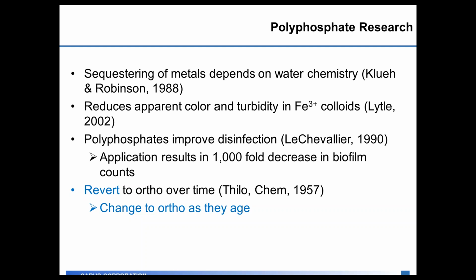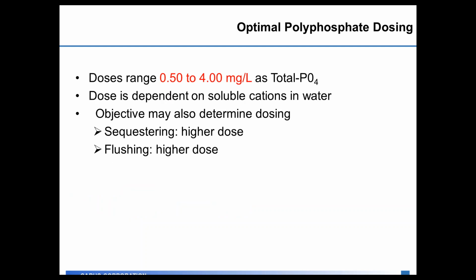One of the last things we know is that polyphosphates do have a shelf life, and they revert to ortho over time. What this means is typically a polyphosphate product has a shelf life of 6 months to 1 year before you start to lose most of the polyphosphate to orthophosphate. So you'll want to take that into consideration when sizing the tanks in your plant for how much product you want to store and how much you're going to use. Typically, optimal polyphosphate dosing is going to be based on how much iron, manganese, and calcium carbonate hardness you have in your water. Typical dosages are anywhere from a half a part to 4 milligrams per liter, and the dose is going to really depend on how much stuff you have to sequester.